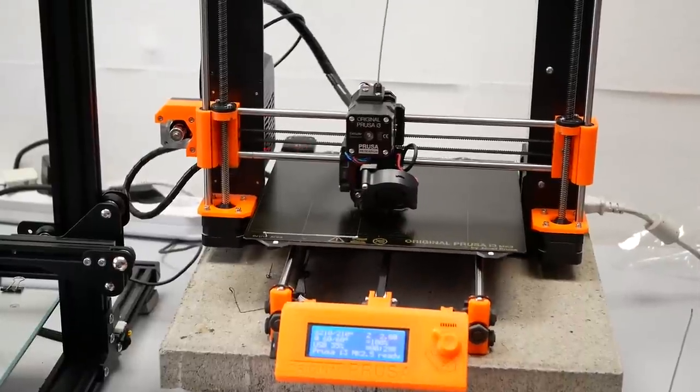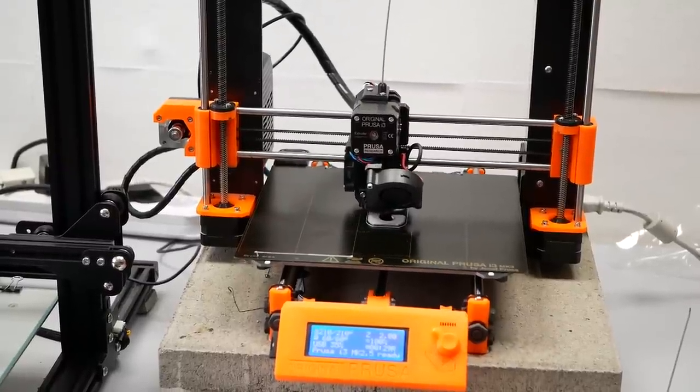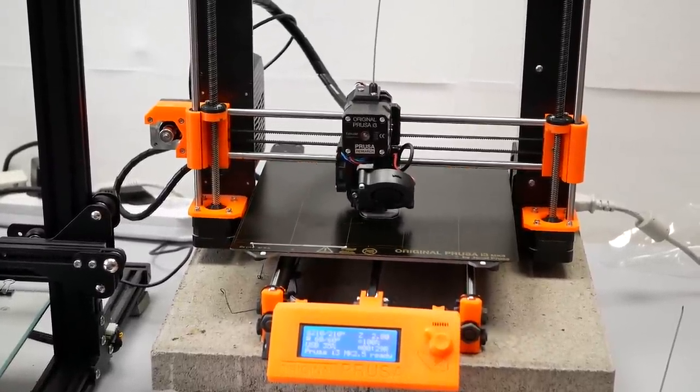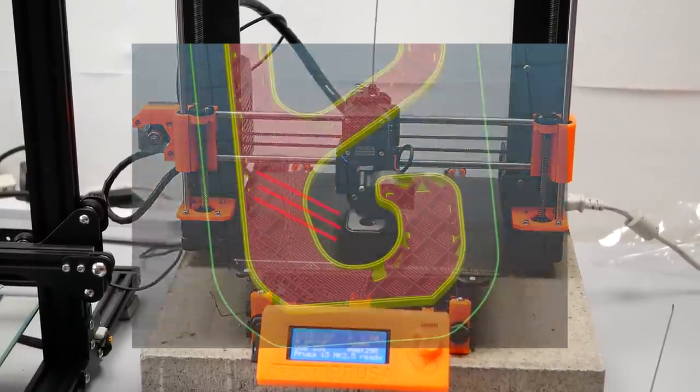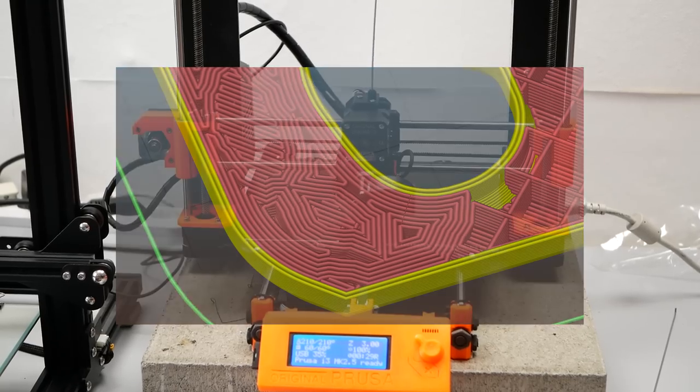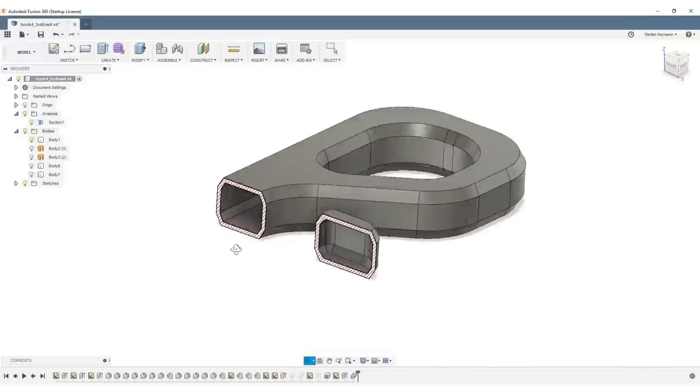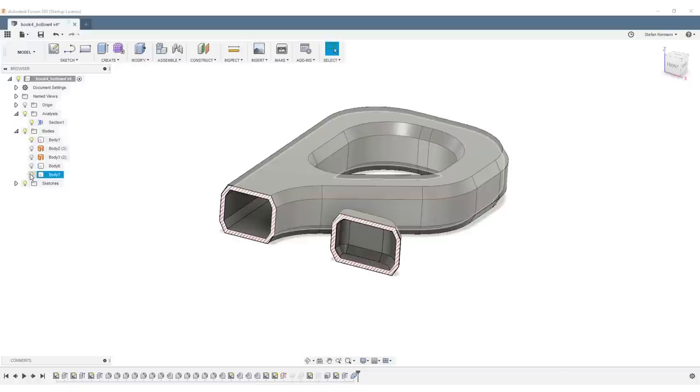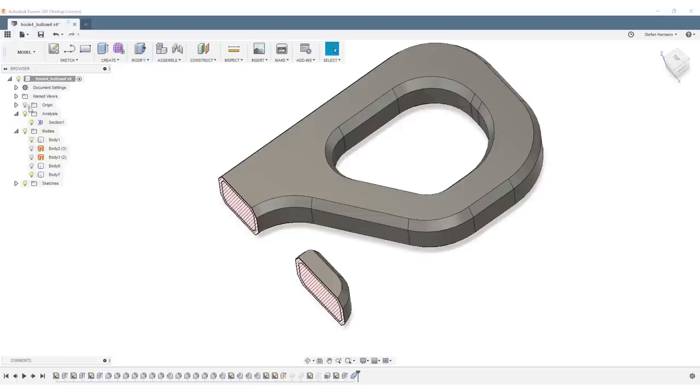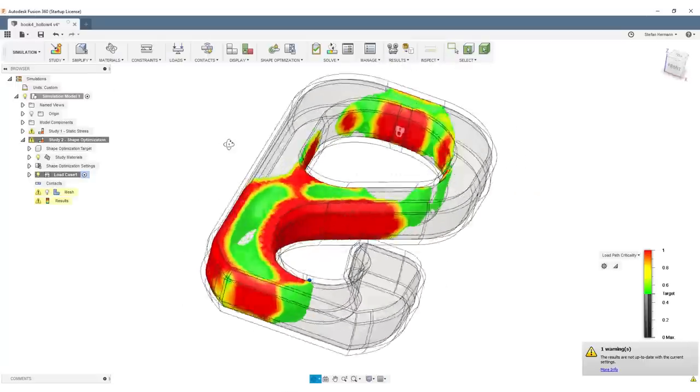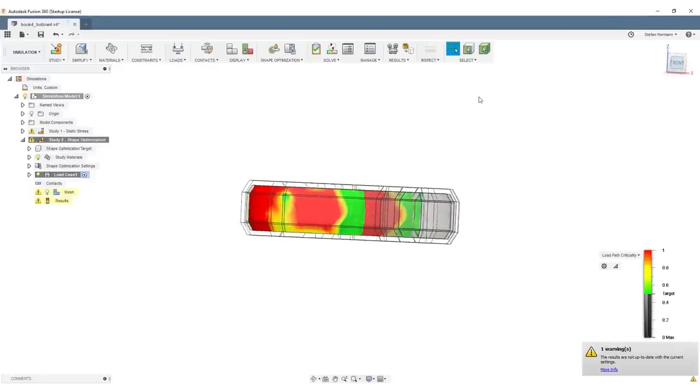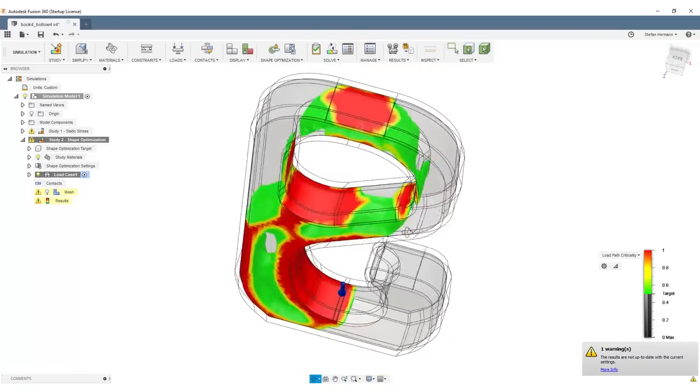We have the smart infill hooks with the modifier mesh from the shape optimization and the maximum stress locations. On these I used 100% rectilinear infill because that usually gives really dense infill, but the plastic strands aren't aligned with the load. I also tried concentric infill, which should make that a little better, but that resulted in quite some gaps. At last, I tried the modifier mesh from a specifically optimized hook where I hollowed the part out and only optimized the internal volume. The outer shell was always kept 100% dense as it will be in reality. This should give us better results but makes creating the model trickier, might sometimes not work at all, and can result in a bad finite element mesh, which is why this wasn't my method of choice.